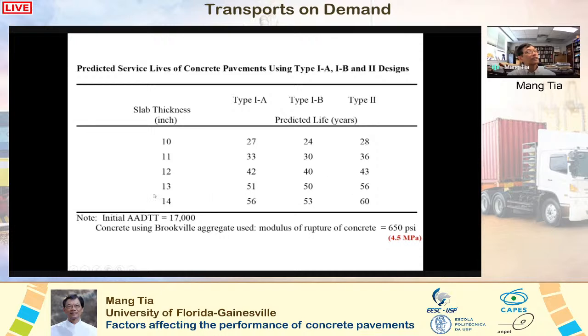Okay, so the key thing is you need to have enough thickness, and you need to have the right concrete, not just strength. In the past we always think about strength, make it stronger, but you need to have the right aggregate, otherwise it won't work. Okay, we have the right aggregate, and of course you need adequate strength. In this analysis, we use a flexural strength of 650 psi, which is equal to 4.5 megapascal. Then it would last for at least 50 years.